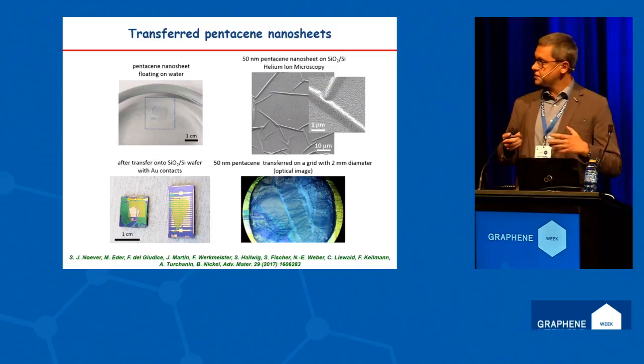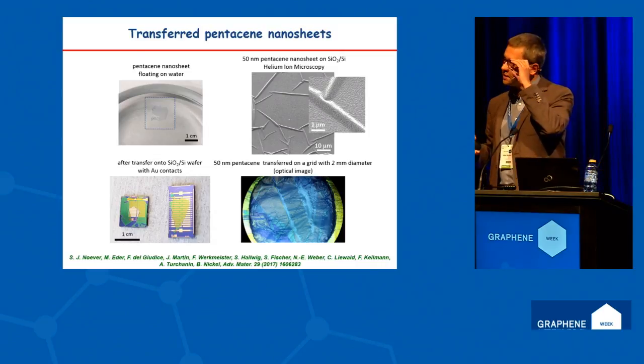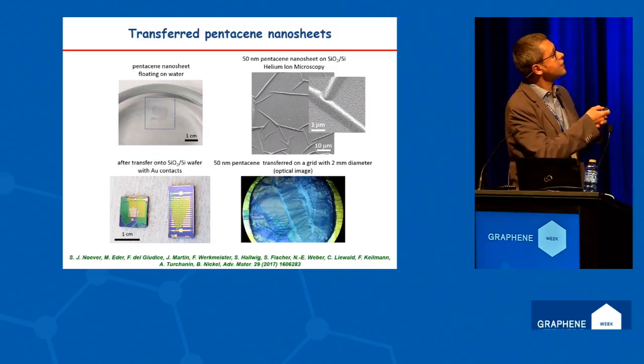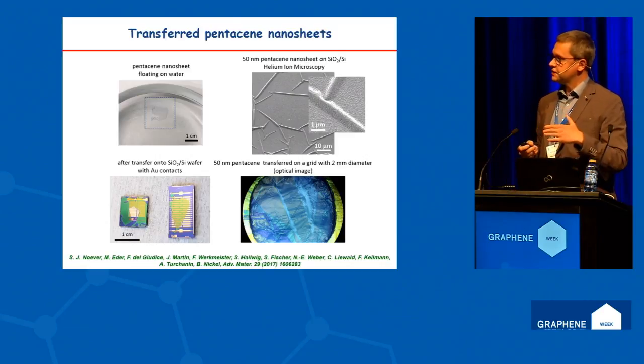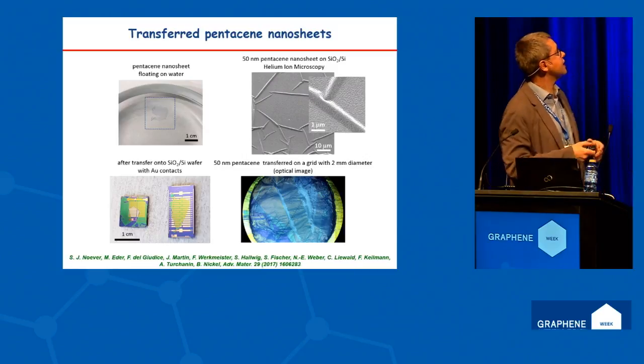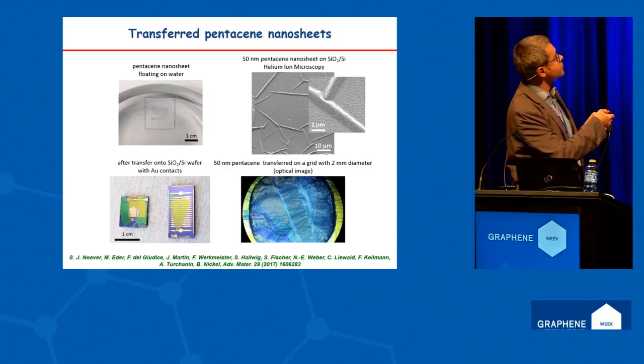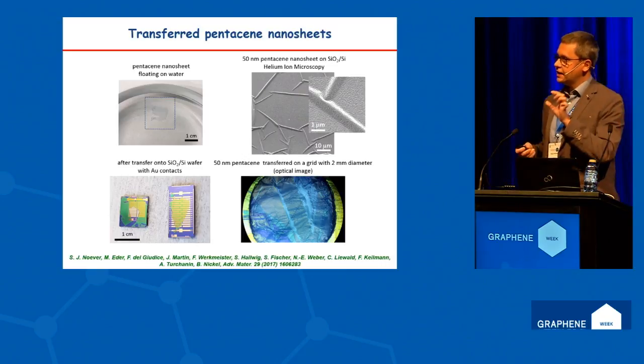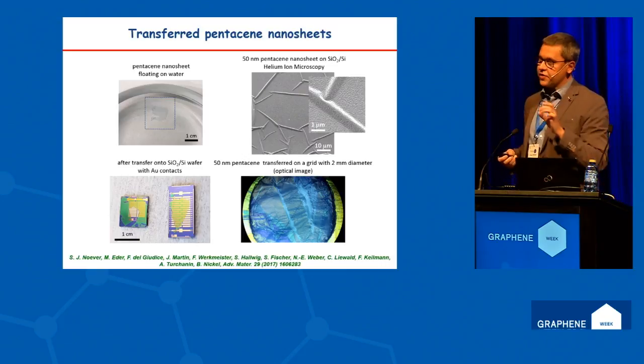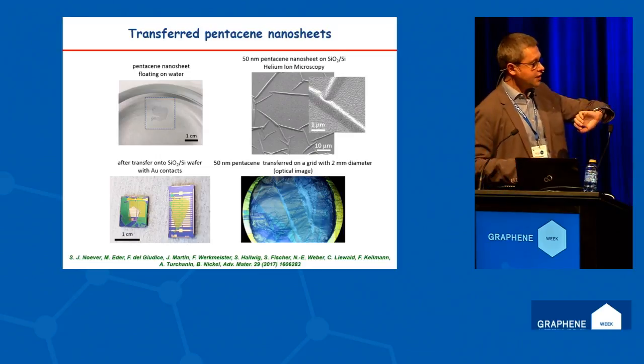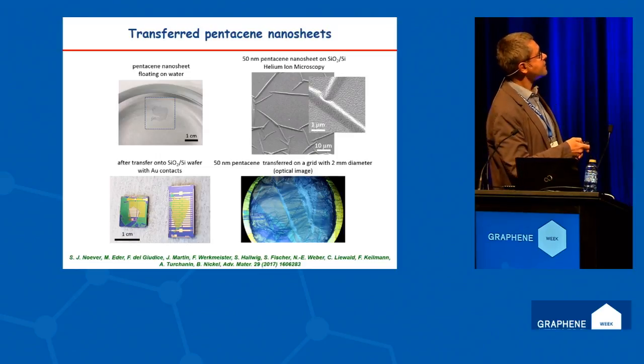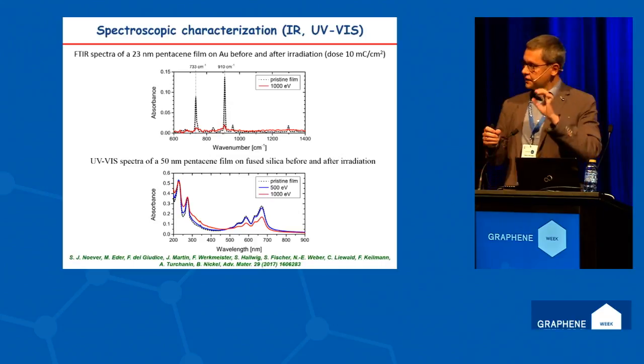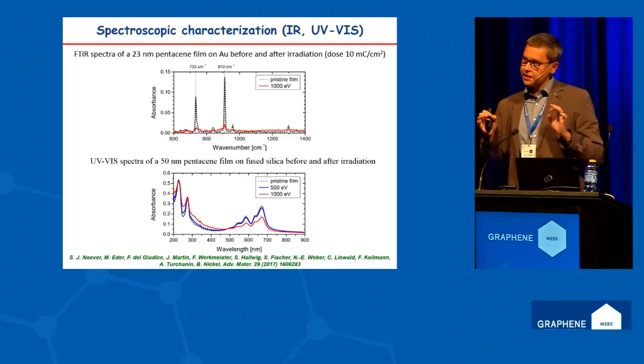So if you zoom in on such a sheet, transferred onto a solid substrate, you can recognize these folds, which is a signature of sheet material. And if you zoom further in, you can recognize a typical terrace-like structure of pentacene, which is completely preserved here. This is an example of transferring the sheet onto device structures, and this is a freestanding 2 millimeter in diameter pentacene membrane on top of such a brass hole. So we studied this process in very much detail.